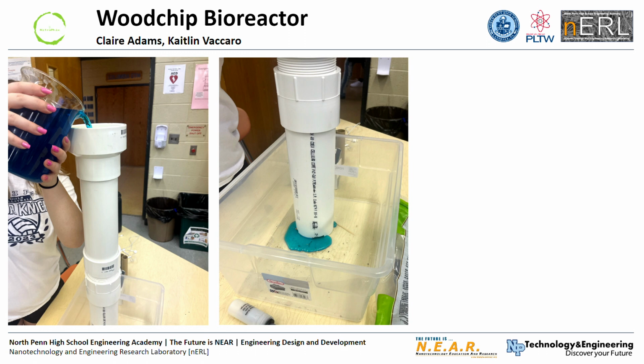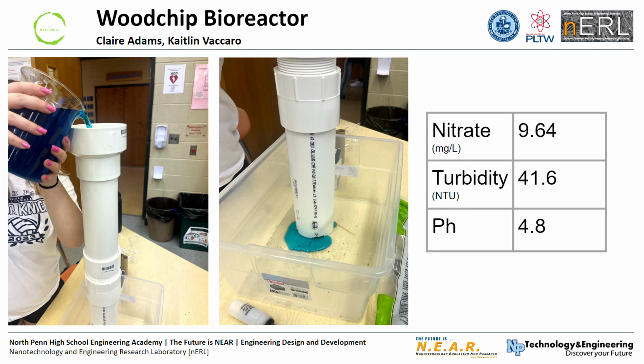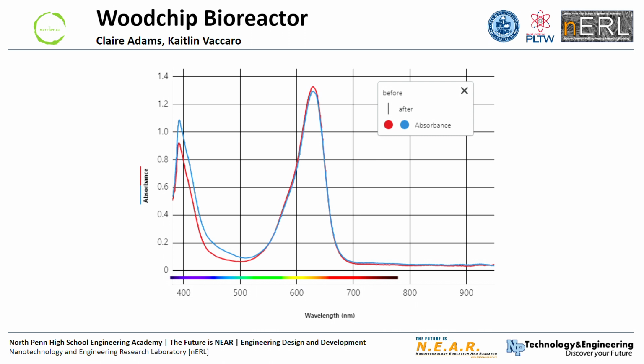Their turbidity had also increased due to the extra wood chip particles in the water, and the pH remained about the same. We also used the spectrophotometer on this experiment, and we found that the only change was between the violet and green wavelength at about 400 to 500 nanometers. We did some online research and found that 220 nanometers was the ideal absorbance wavelength for nitrates, and our graph was fixed to 400 nanometers, so we could not accurately use this for our research.